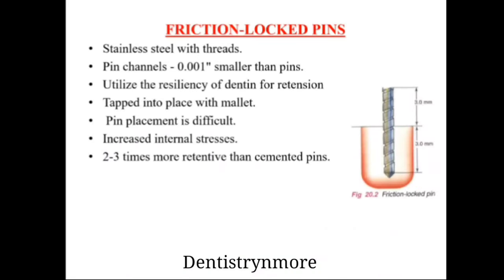Next one is the friction locked pin. This is a stainless steel pin with threads, and the pin channel is 0.001 smaller than the pin. Here the disadvantage is that pin placement is difficult, and internal stress is increased, but it gives 2 to 3 times more retention than the cemented pin. The figure of the friction locked pin is seen here.